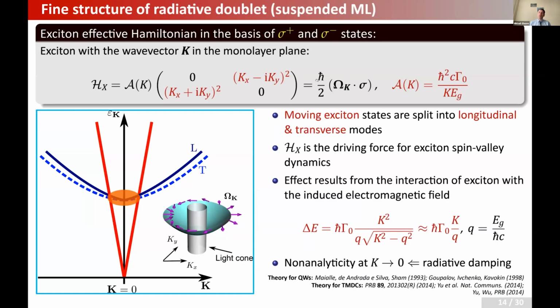In fact, the coupling of excitons with the induced field in that case would provide you the radiative decay. And that is why the general expression for this exciton Hamiltonian, or for this exciton self-energy, is a little bit more complicated. But anyway, for practical purposes, you can forget this very small radiative cone and only discuss the excitonic states with sufficiently large wave vectors. These excitonic states are split, as I have already explained to you, into the longitudinal and transverse states. In the longitudinal state, it is linearly polarized along the exciton wave vector, so the microscopic dipole of the exciton oscillates along k, and for the transverse state, it oscillates in the plane, but perpendicular to k.